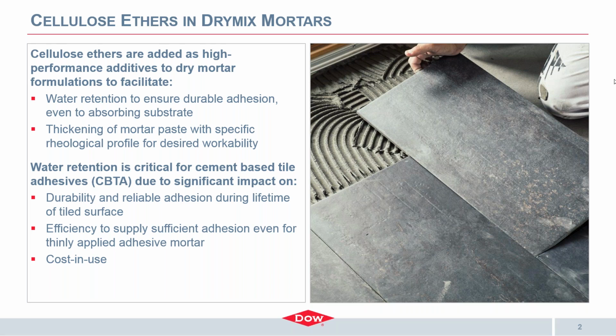Water-soluble cellulose ethers are used as high-performance additives in dry mix mortars, and at a low dosage, about 0.5%, typically less, they significantly improve the water retaining capability of a mortar. And water retention is critical for thinly applied mortars and on absorbing substrates, because water is required for proper hydration and final strength development of cementitious or gypsum-based materials.